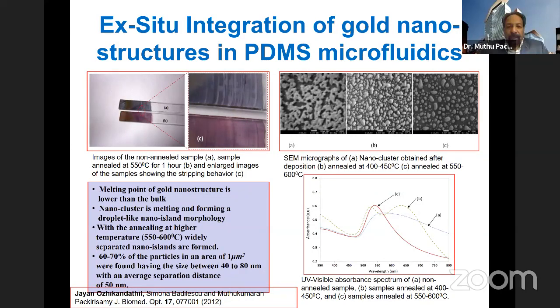So you can see here the ex situ integration of gold nanostructures. What you see on the right-hand side is basically the gold nanoparticles, and they have been subjected to thermal annealing, through which you can change the morphology of the nanoparticles. So you can change the shape, size, distribution and density of these over whatever substrate you want. Why do we have to do it?